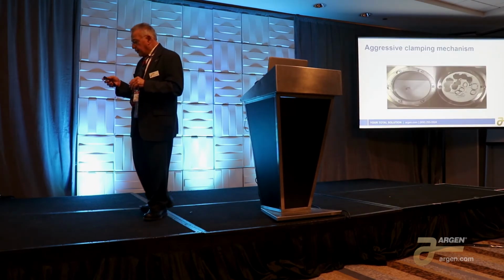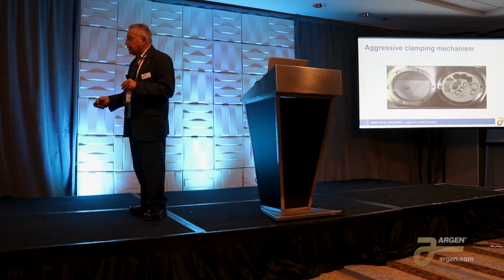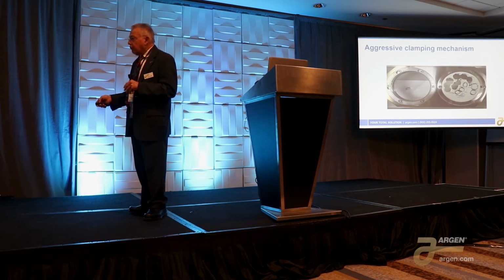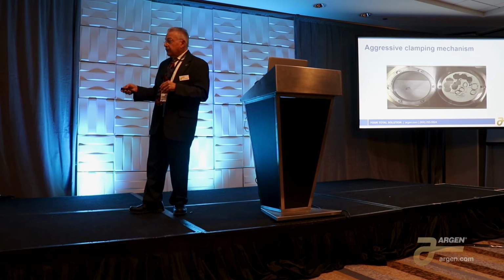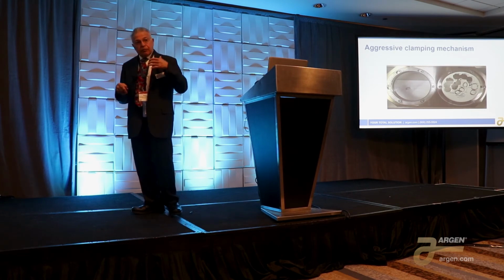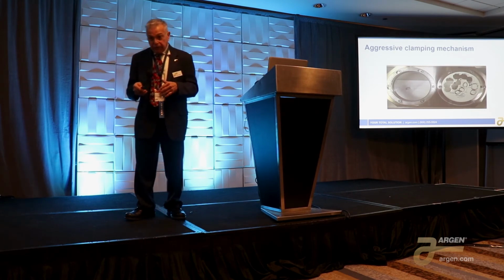Okay. Now this is the most aggressive type of clamping mechanism, because it's all metal against the ceramic. And again, you can see a beautiful crack here. And that crack was because these two were tightened at a greater pressure than the other four. So this could happen, and it happens due to excessive clamping forces.